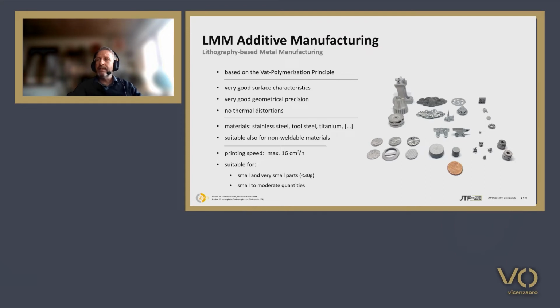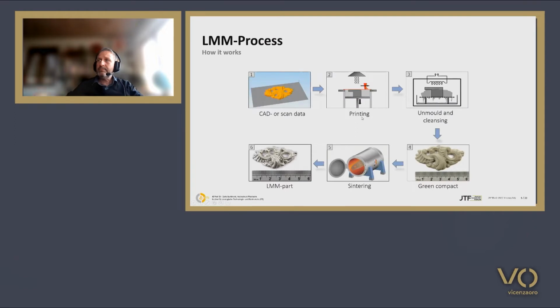There's one big difference compared to laser sintering. It's only suitable for small and very small parts. Currently, the rule of thumb is around 30 grams, but that's, of course, depending on your material. 30 grams of titanium are obviously much bigger than 30 grams of gold. And it's suitable for small and moderate quantities.